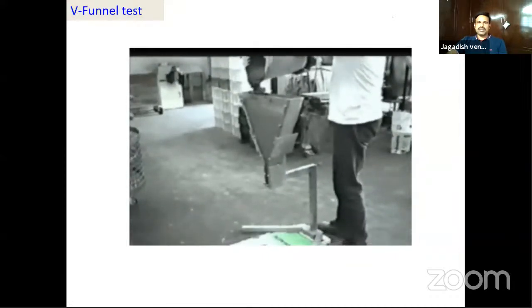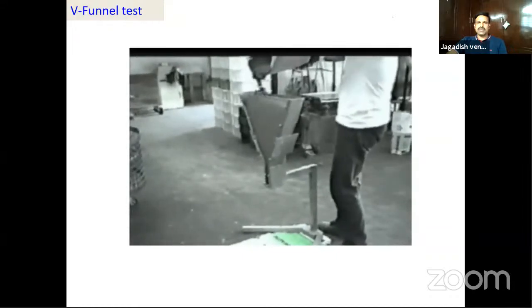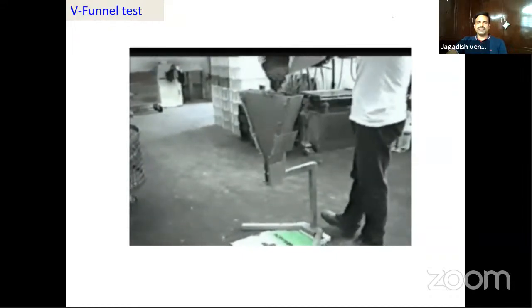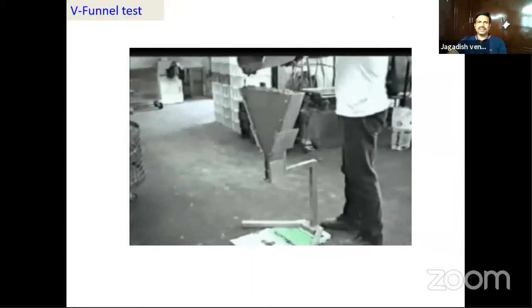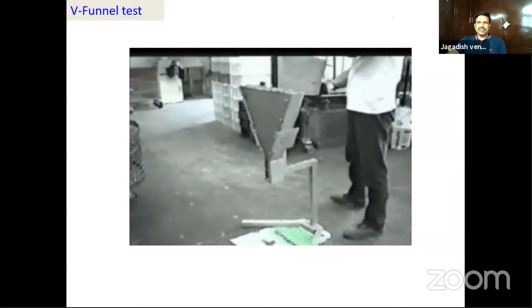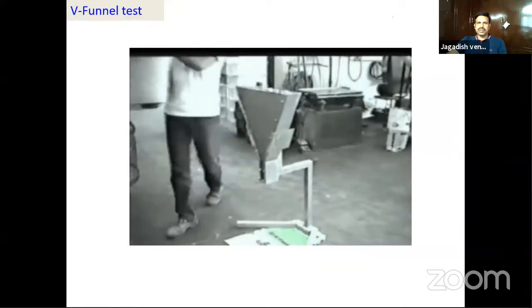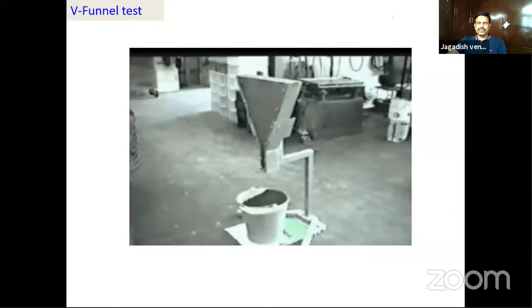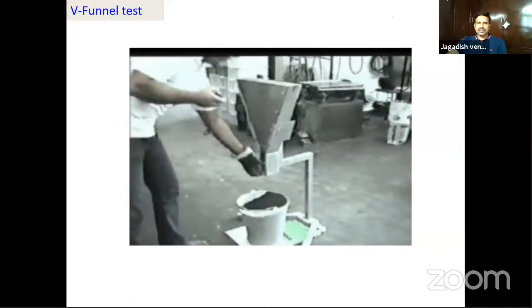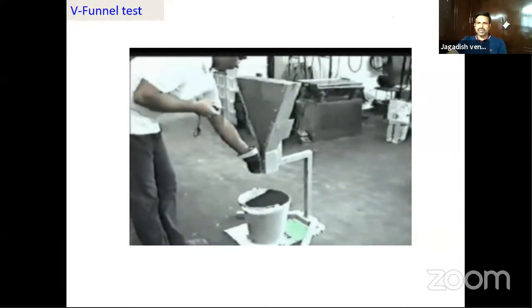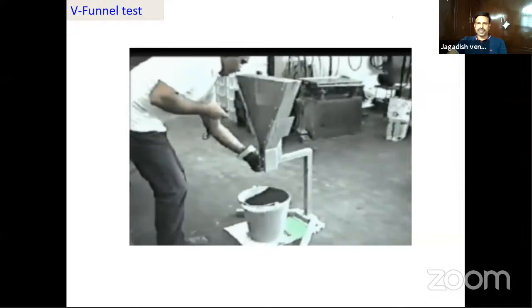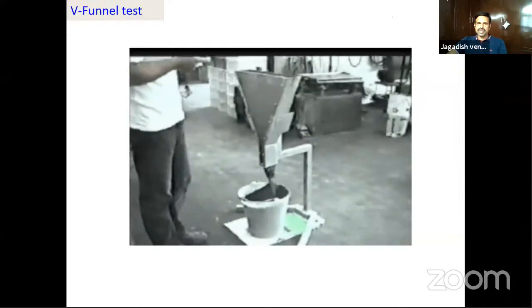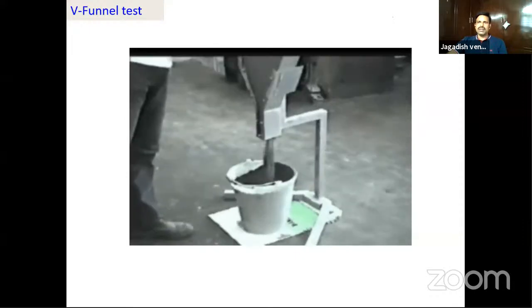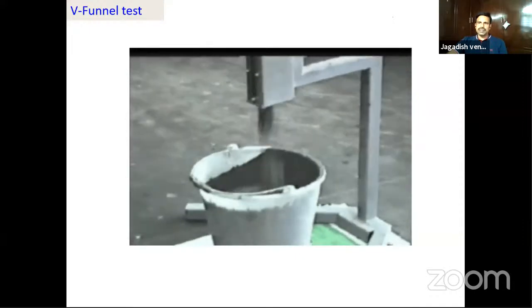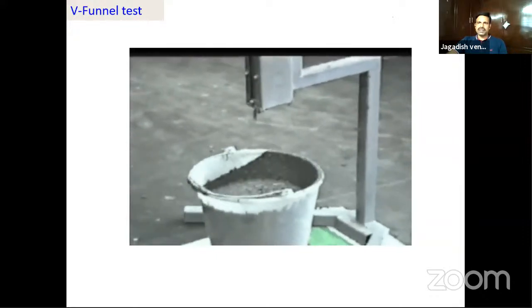You just have to pour the SCC into the V-funnel, and be ready with your stopwatch. Then you remove the bottom door, pull the bottom door, and measure the V-funnel time. Similarly, you wait for 5 minutes and you can measure the V5 minutes flow time also.